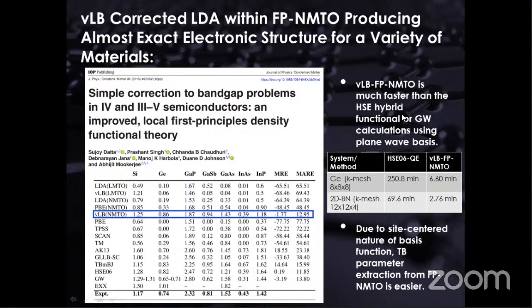An alternative and a very fast way, as we see in this right panel, can be done using the VLB correction into LDA and implementing it in the full potential NMTO system. We have done this on different types of materials, and we have found success. You can see that the MRE value, that relative error value, is quite low for VLB NMTO.